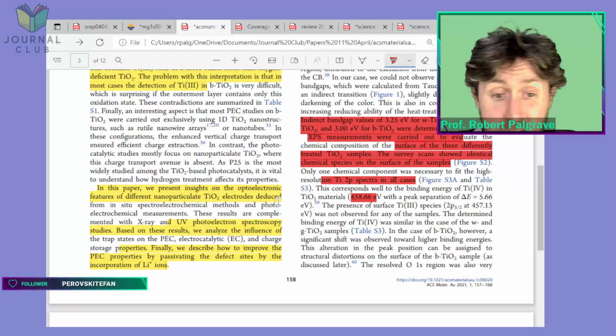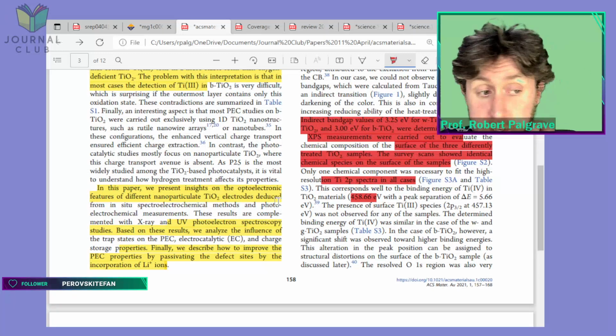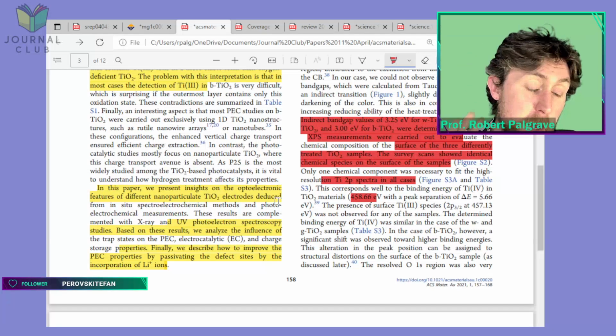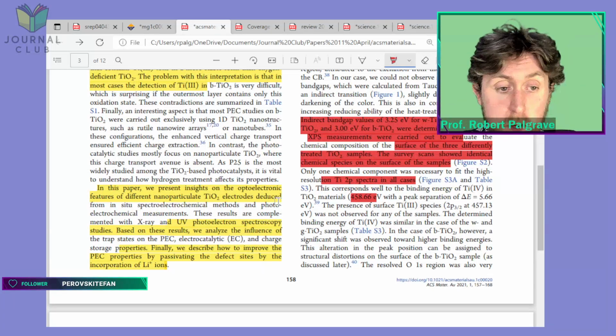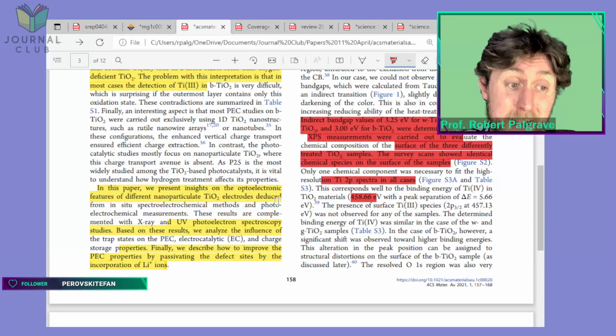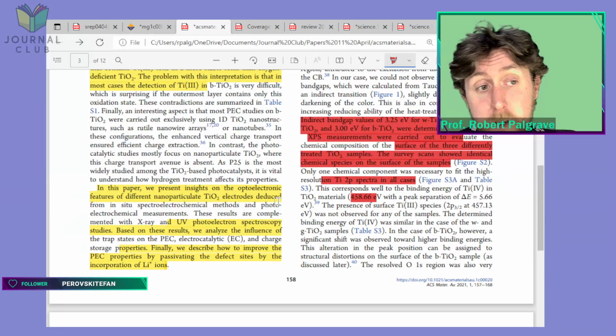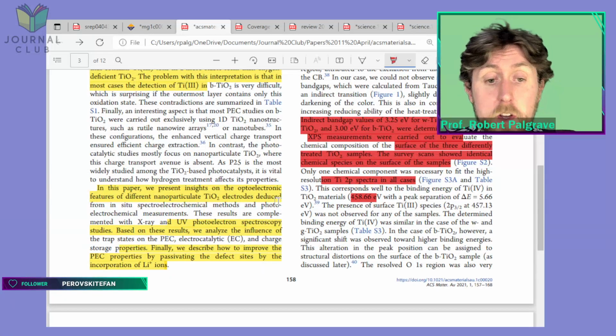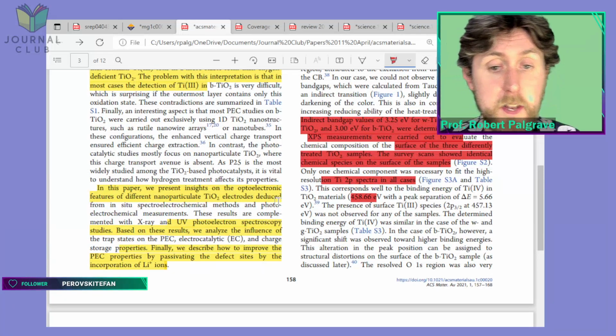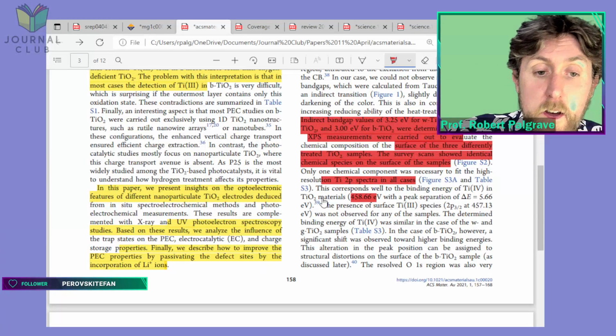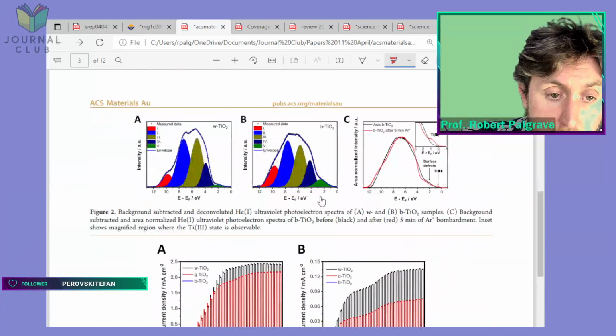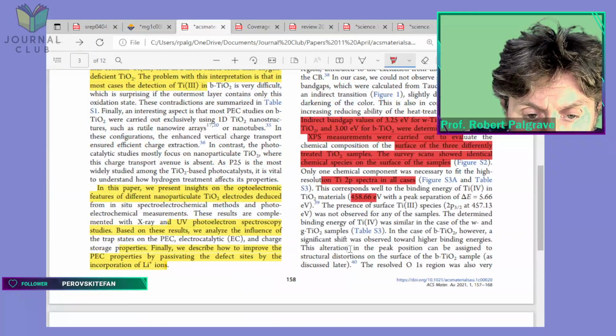And I think they see an increase in the binding energy of the titanium peak. That will correspond to putting more electrons into the material, to electron doping the material. And again, that's not impossible that hydrogen is doing that. In various different ways hydrogen could go in. You could definitely be adding electrons in, and so that could correspond with the shift in titanium peaks that we see. Anyway, they discuss that later.